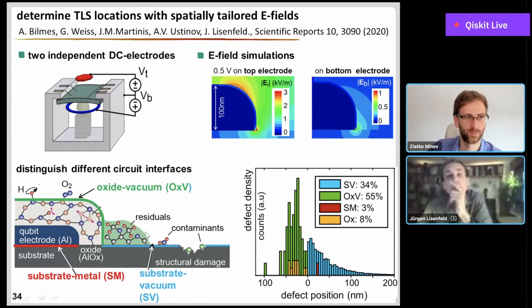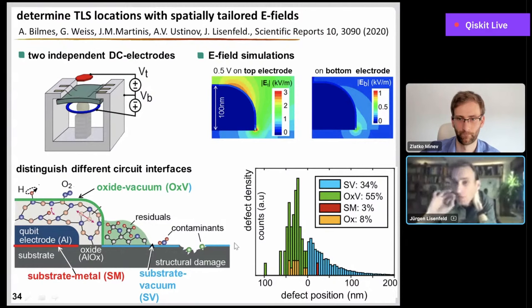I would not say it doesn't matter. What we found is just that the defects that we detected with our qubit were those defects which were at the very edge here, because if you had defects inside this oxide layer, they would have a much weaker coupling strength because of the dielectric permittivity of this material. And that's why the defects which we found were not compatible with that.